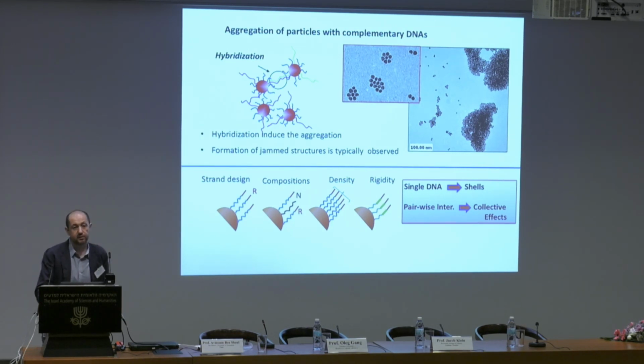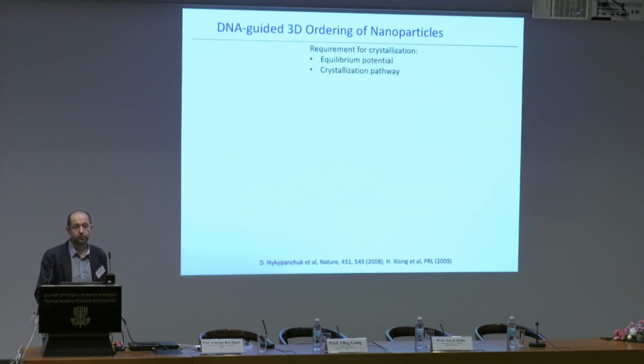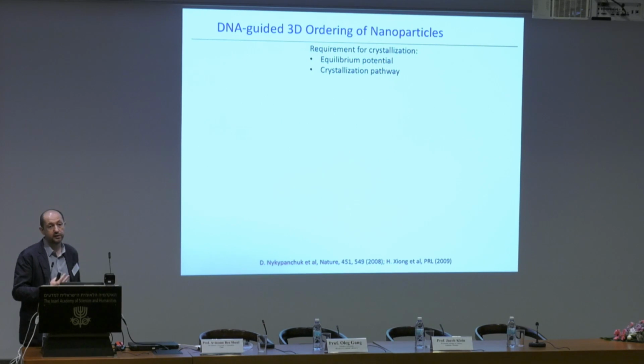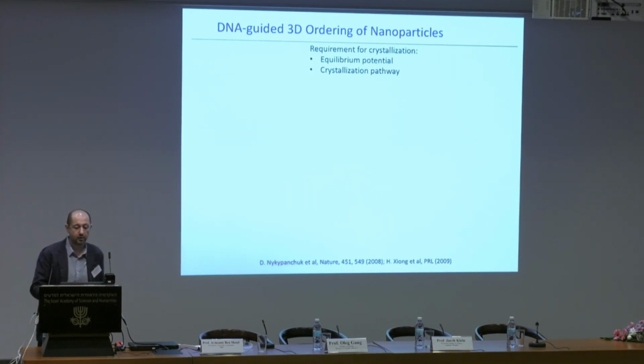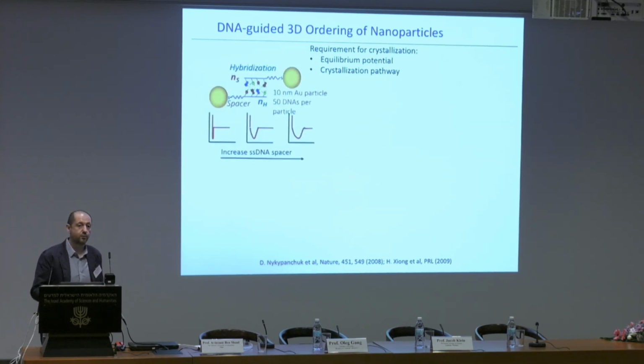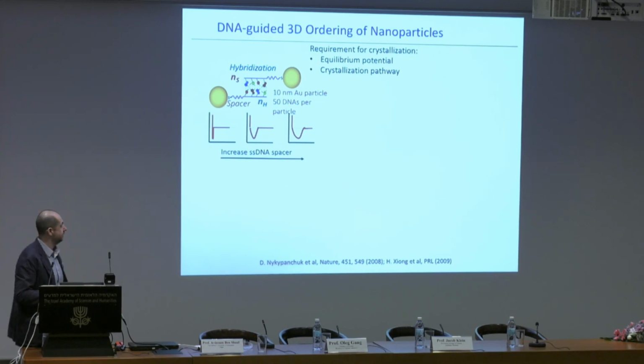And so when we started to think a bit more rationally about what is really required to crystallize particles using DNA as a driving force for self-assembly, we started to think that it's necessary to have an equilibrium potential which allows for crystallization. From another point of view, it's necessary to establish a proper pathway. From the point of view of equilibrium potential, one can imagine a potential not necessarily very suitable, because it's very difficult to crystallize when you have such strong interaction, essentially no repulsion. This potential might be too soft, and there is not much difference between metastable disordered and stable ordered phases, and this might be more appropriate.